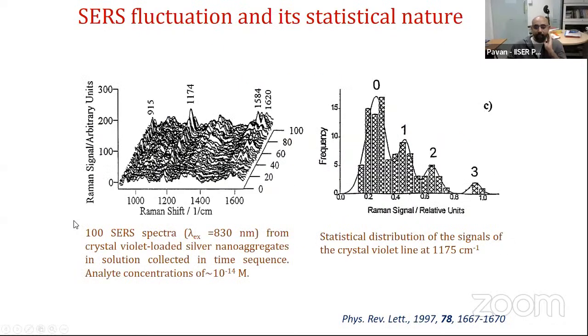In fact, it dates back to around 1997, a very famous PRL paper where the SERS fluctuation was studied in this particular situation. And interestingly, the statistical distribution of a particular molecule, in this case, a crystal violet molecule, was studied quite a lot. But it happened so that there were some errors in this particular experiment, not actually an error which is intentional, but the interpretation of this particular experiment required a little bit more than just a conventional Poissonian statistics kind of an approach to understand this particular interaction.